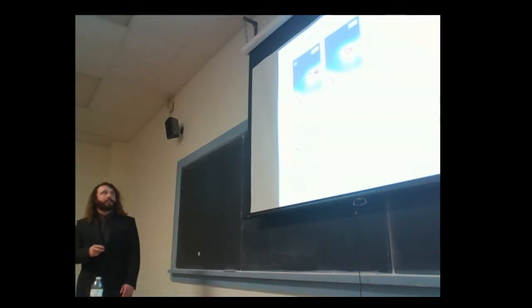Okay, so this is connected to my measurements like so. This is a before. This is a snapshot before the pump pulse, and this is a snapshot after the pump pulse. This is the difference between the two, where this is the extra electrons and this is the extra holes. So if we were to draw a box around these, then we could average all of the excited electrons or the excited holes through time to get something like this, where the blue is the excited holes and the red is the excited electrons.